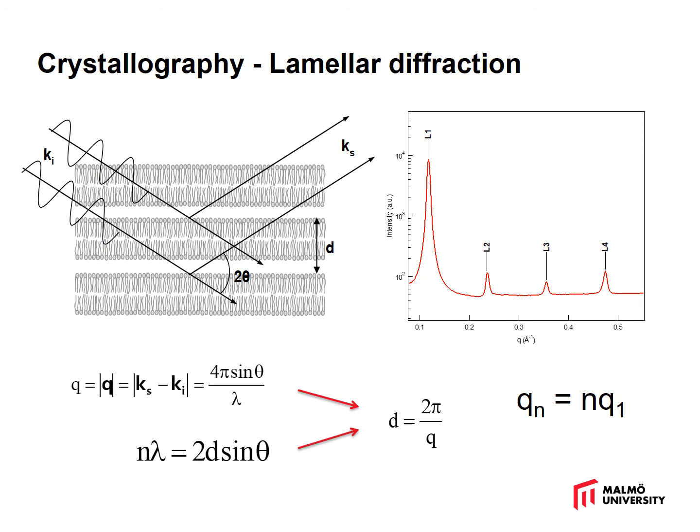So this is the simplest kind of unit cell. It's a lamella unit cell, and the interference that's generated by this periodic spacing gives a series of peaks which are equally spaced apart. And this is very characteristic of a lamella phase. And from the peak positions, one can do a linear regression and get the d-spacing. And you might like to think about how one would estimate the error from that, the kind of plot that one would use.